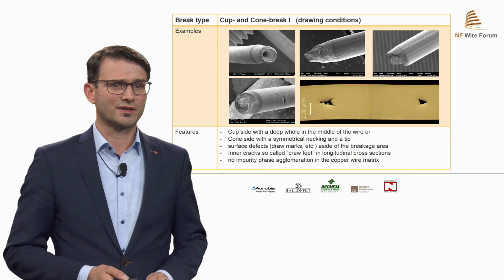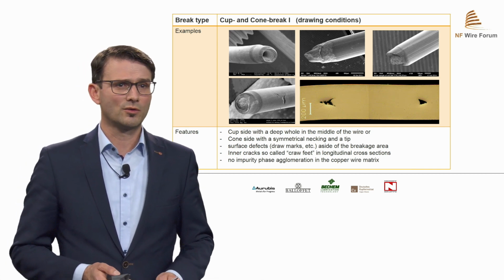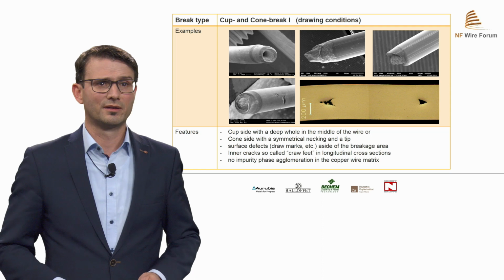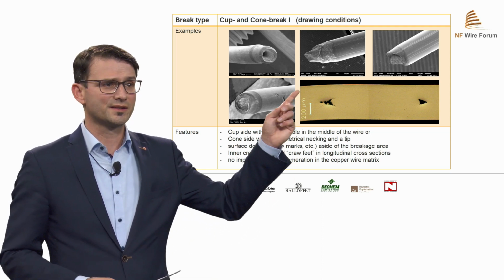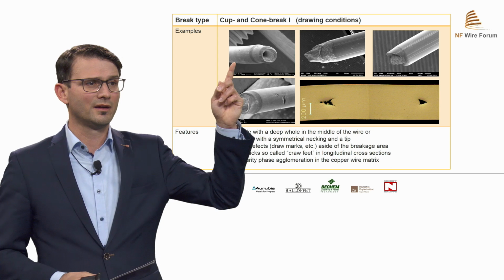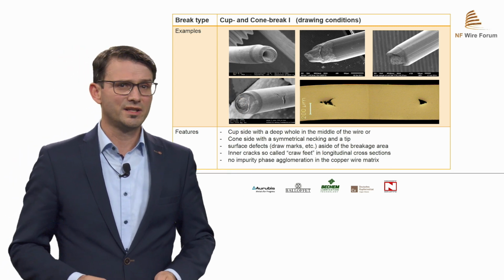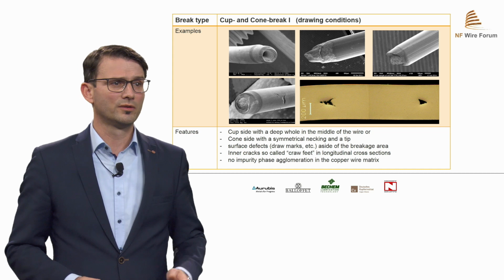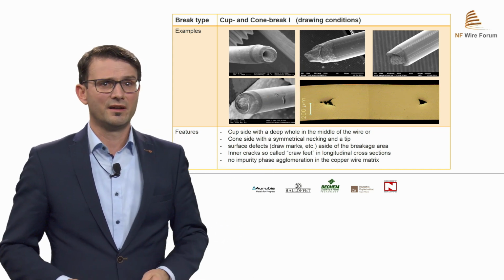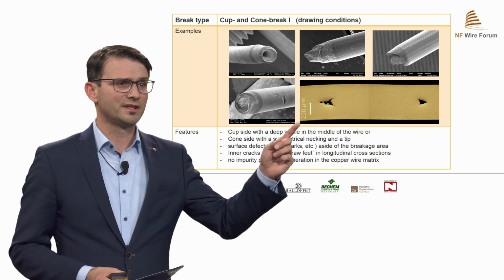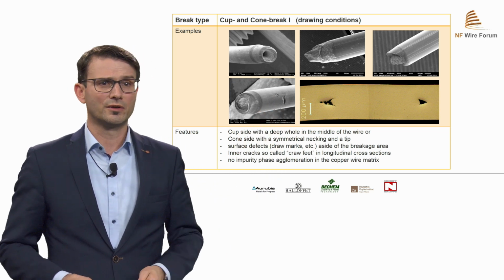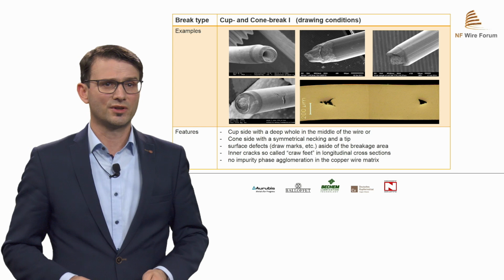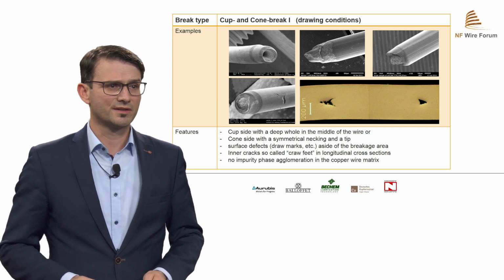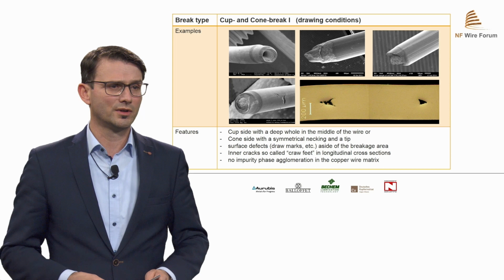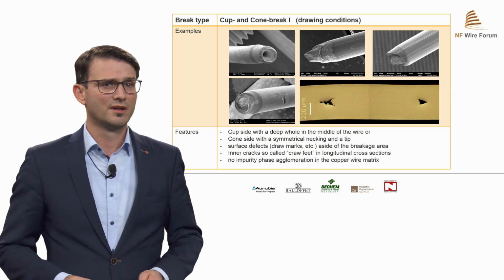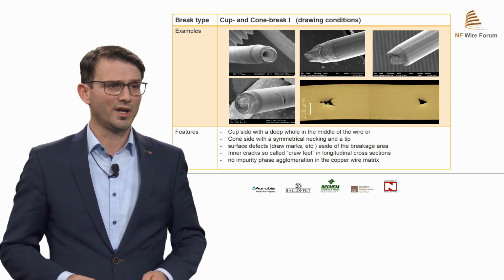Let's look at the features of a wire break, the so-called cup and cone. You see on this side here a deep hole in the cup side, a cavity in the middle of the wire, and a cone, which is here. You see a necking tip. You see surface defects, as on this photo. And when you do a longitudinal metallurgical cross-section, you see the so-called crow feet. So no impurities, no phase agglomerations in the copper wire matrix.